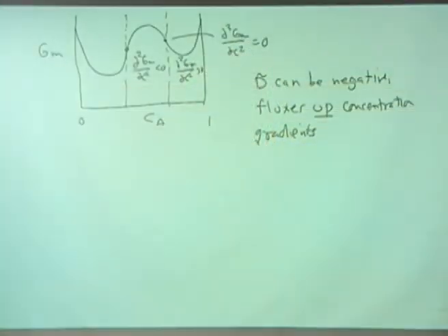Let's talk about one of the problems that we encountered here. And that was this idea of, and what the ramifications are, of the fact that we can have this interdiffusion coefficient being proportional to the second derivative, and with the second derivative being negative implies that the diffusion coefficient could be negative. And so I want to talk about some of the ramifications of that and how we can address that problem. And so what is the idea of D tilde being less than 0?